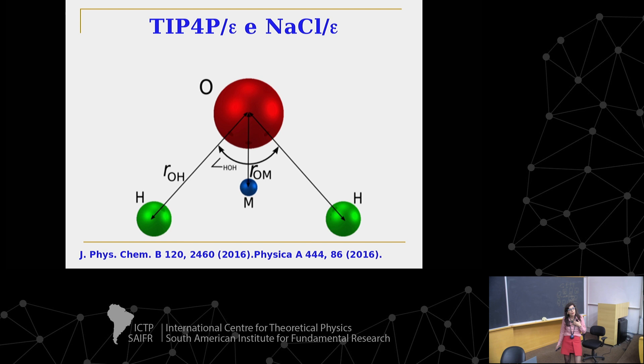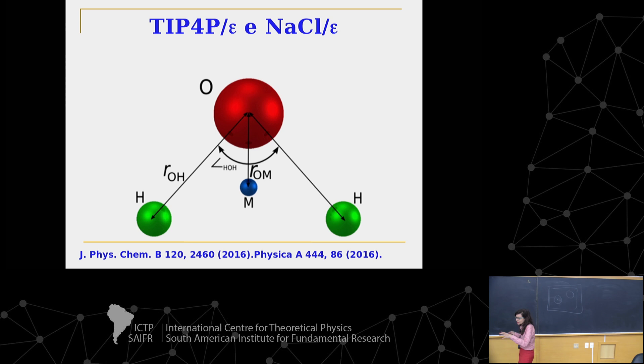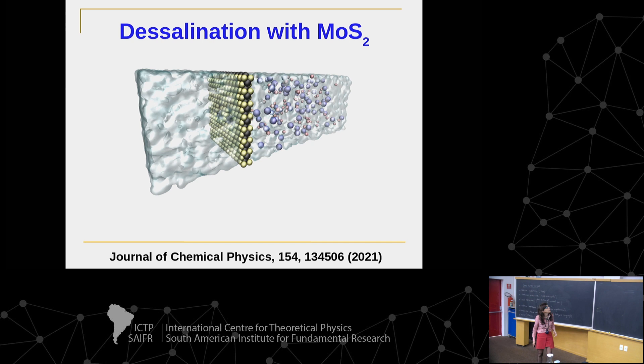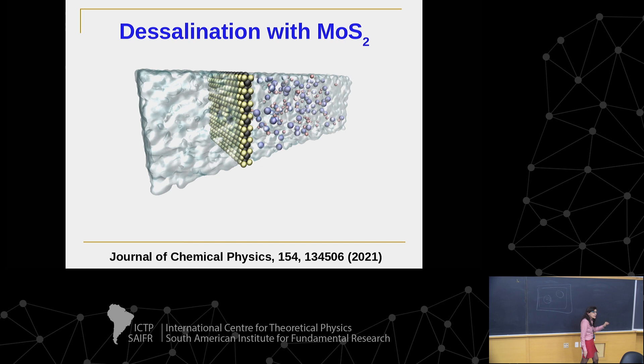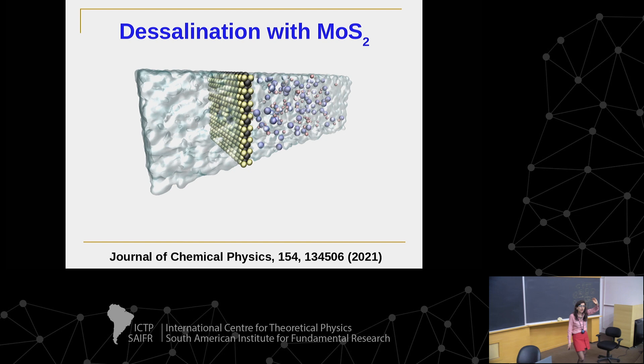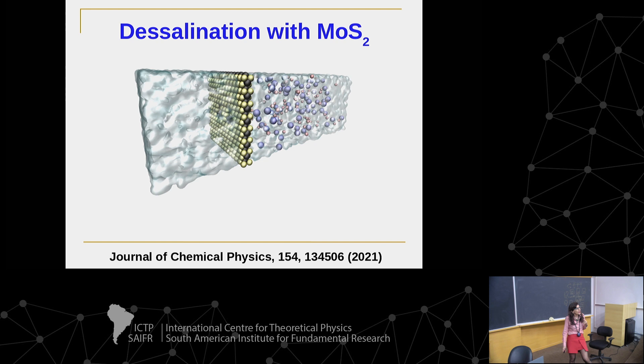Most literature models don't focus on the dielectric constant, but we need it to understand systems when salt is present. So we developed models for both water and salt, and created a simulation where one side has water and salt, pressure is applied as in a desalination plant, and water passes through a nanopore in molybdenum disulfide (MoS₂). We chose MoS₂ because it has a charge distribution — neutral overall but with a dipole — which we believe helps water pass through while generating a favorable interaction.